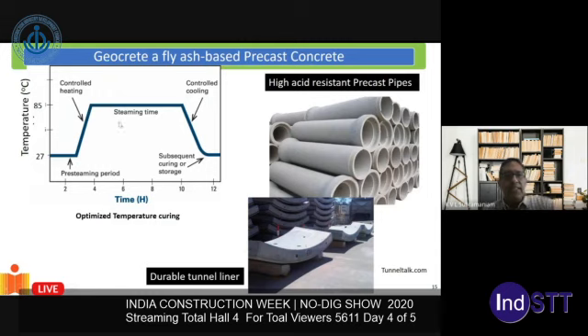And this is the ideal temperature for geopolymerization to happen. We can actually accelerate the geopolymerization and deliver the strength much quicker, as I had shown before. Because these geopolymers produced from fly ash have a very high acid resistance, they are ideal candidates for making precast pipes, which can be used for sewage and even for transporting water in the urban setting.